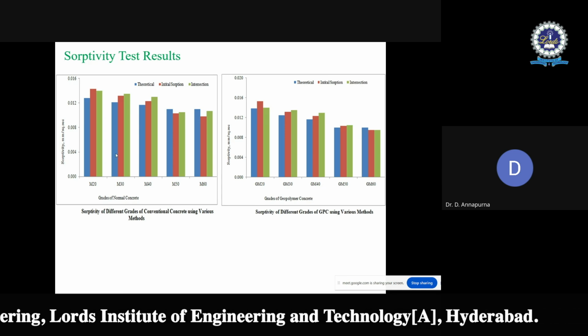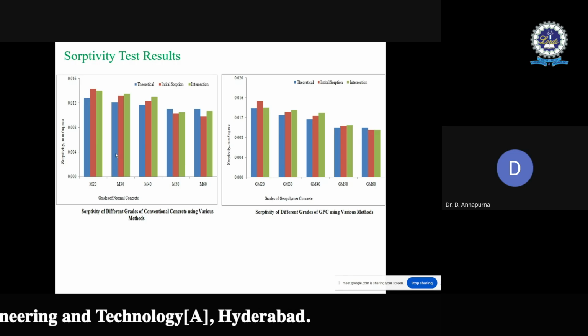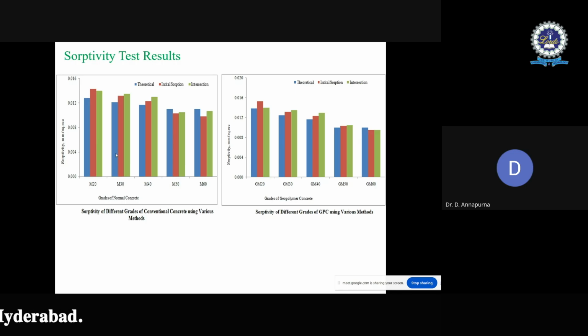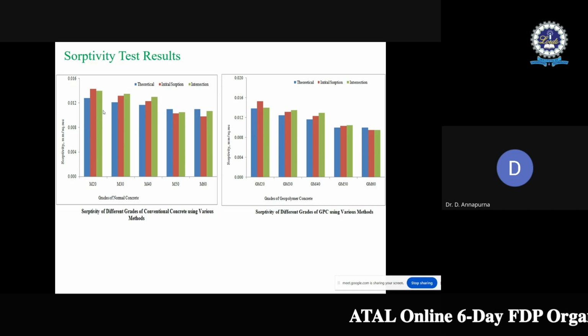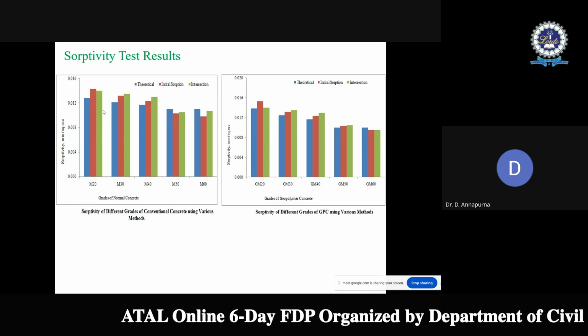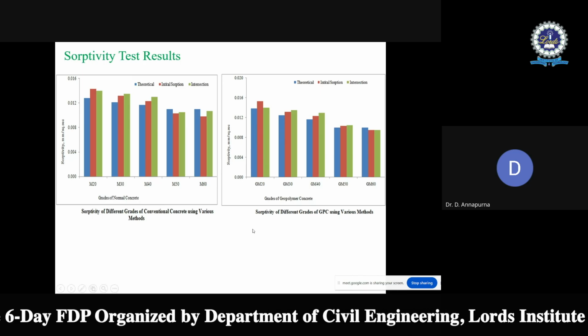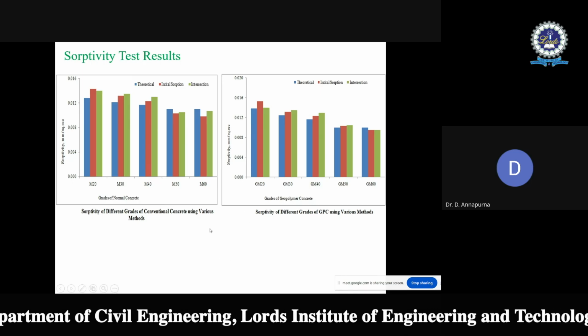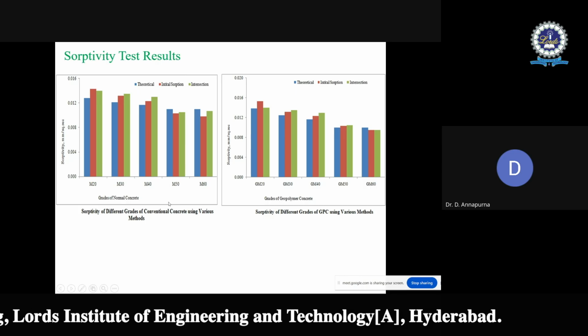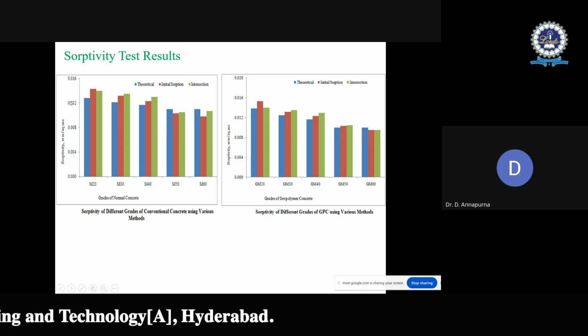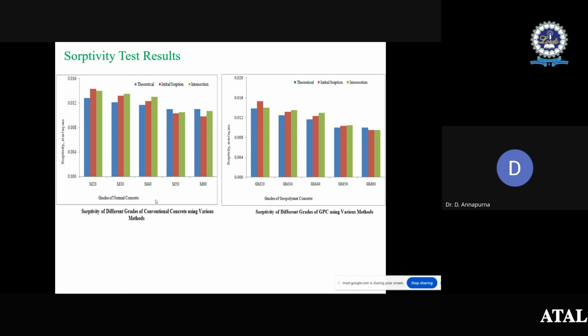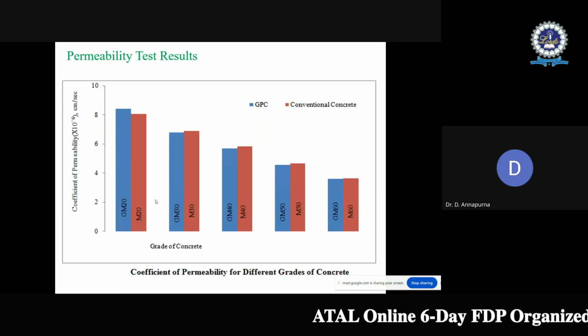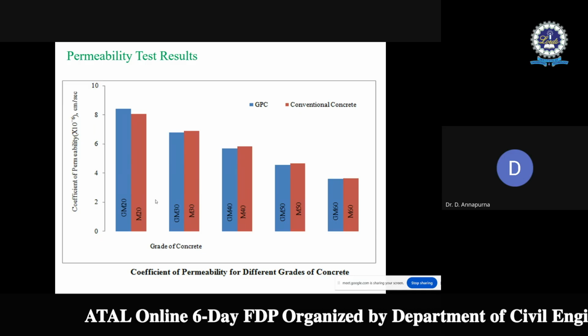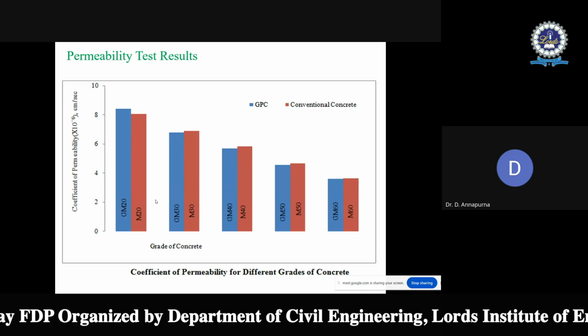based on that the sorptivity value will be achieved. So here it is mentioned that the sorptivity index of geopolymer concrete is less than 0.2 mm per square root minute. It is considered to be acceptable quality in terms of water tightness. As per the earlier literature, it is specified that if the sorptivity index is less than 0.2, and if you look at it, it is less than 0.2 only. So it is within the highest acceptable limit in terms of water tightness. So the proposed geopolymer concrete has water tightness nature.